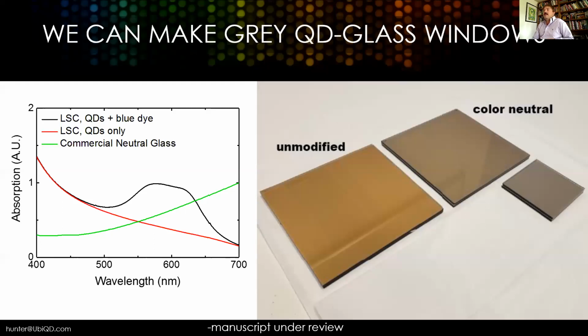Architects will tell you that this would have been very popular in the 80s when bronze was the color of the day, but not anymore. Nowadays, architects want more of a gray, a true gray, neutral color. So we've purchased quite a bit of commercial glass, and you can see this green curve on the left as an example of that, where the absorption is actually stronger on the red side than on the blue, and that makes it look a little bit bluish gray.